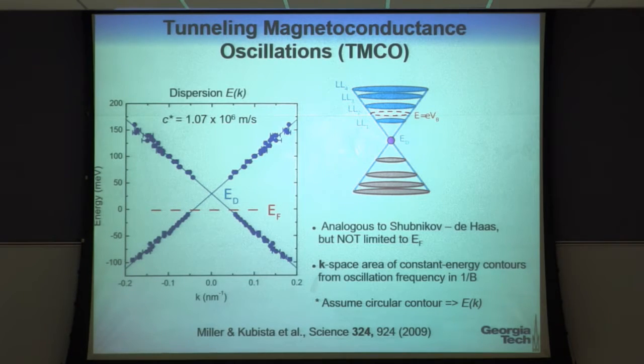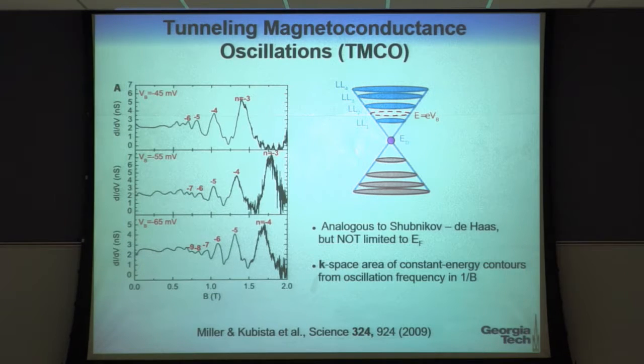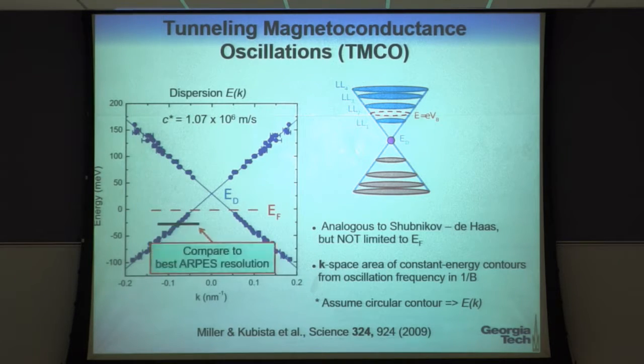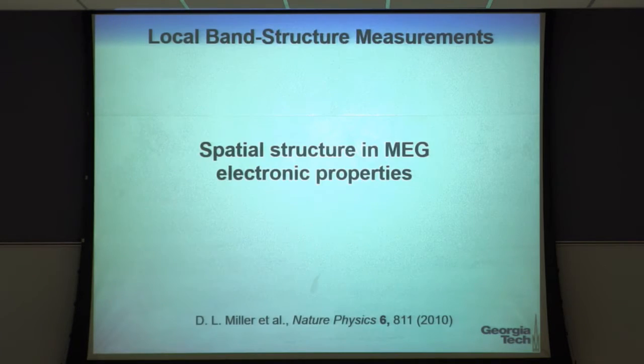These oscillations that you see in the magnetoconductance, that's the dI/dV, as a function of magnetic field, are analogous, for those of you who know, to Shubnikov-de Haas oscillations. It's a conventional means for measuring Fermi surfaces. And from the period in 1 over magnetic field, you can actually get the area of those discrete states in k-space. You can find the k-space orbit. And the result is that we get the Dirac cone, and compared to the best ARPES resolution, it's really, really good, both in energy and momentum. We didn't get very close to the Dirac point because, as I said, we have to do this in a closed loop manner, and we don't want to crash our tip.